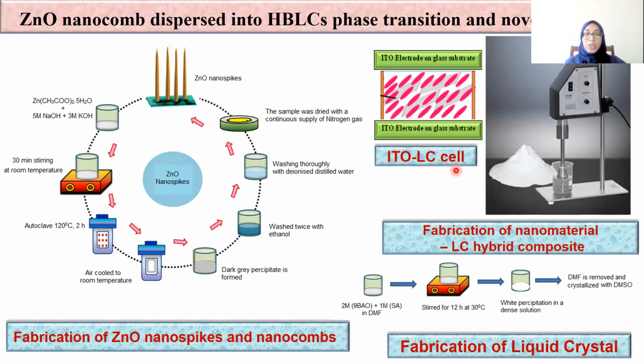Here, the ITO liquid crystal cell is again fabricated. The indium tin oxide, that is ITO electrodes, are of dimension 4 millimeters squared. And here there is a spacer which forms a gap in between them. The liquid crystal cell is now kept on a hot plate and heated at a rate of 5 degrees centigrade per minute. The synthesized hydrogen bonded liquid crystal dispersed with zinc oxide nanocomb is spread into this heated cell by capillary action.